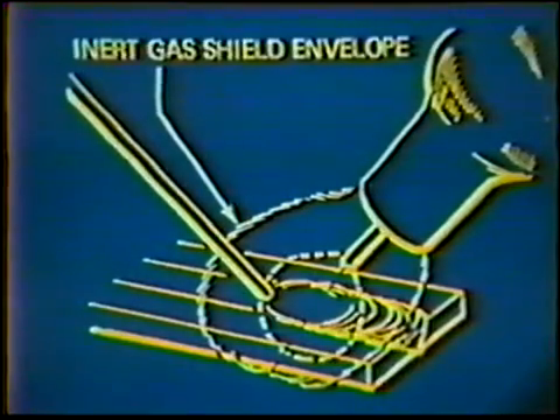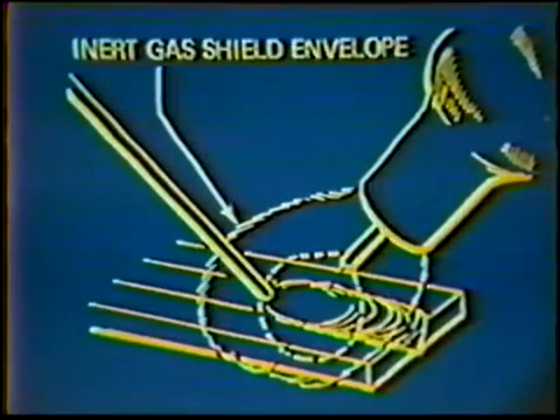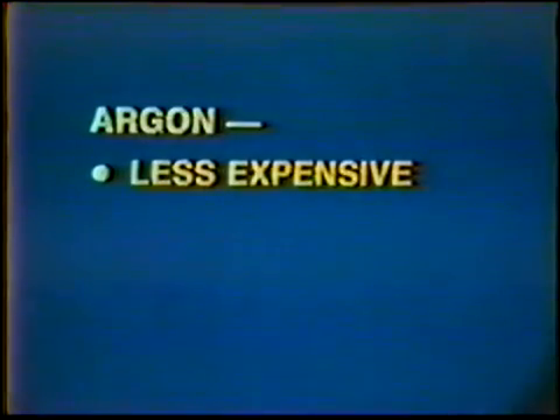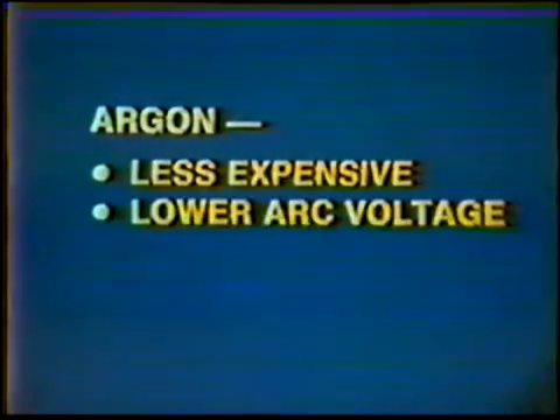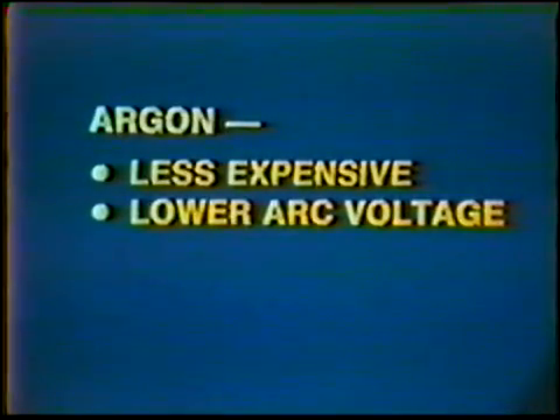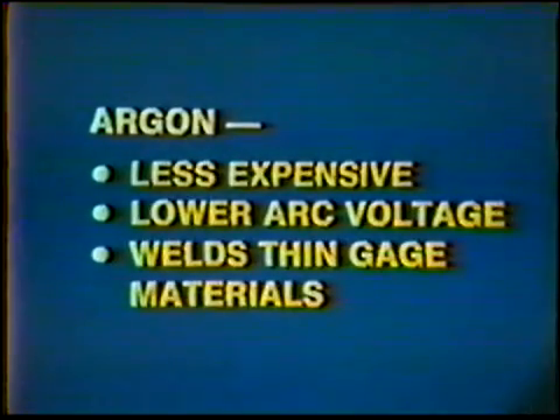The shielding gas protects the weld puddle and tungsten electrode from oxidation during welding. The two most commonly used shielding gases are argon and helium. Argon is less expensive than helium and is the gas most often used. Argon also produces a lower arc voltage than helium at a given amperage. This makes argon excellent for welding thin gauge metals where low arc heat is necessary to prevent excessive root bead penetration.